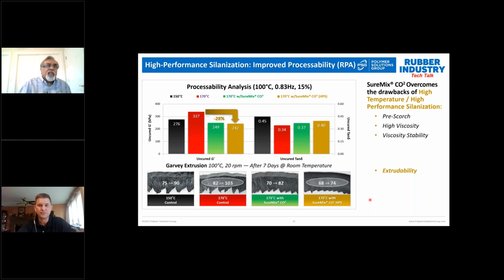Just before we go across, I just wanted to point one thing out. If you look at the Mooney viscosity after 7 days for the one with high performance silanization, it's at the same Mooney viscosity of the 150-degree control as mixed. This is also a challenge for a lot of silica compounds, which require remilling if you store the compound before you can extrude it. It doesn't matter what the application is. The higher the silica loading, the more the requirement. But when you add SureMix, even after a week, the processability is not compromised.